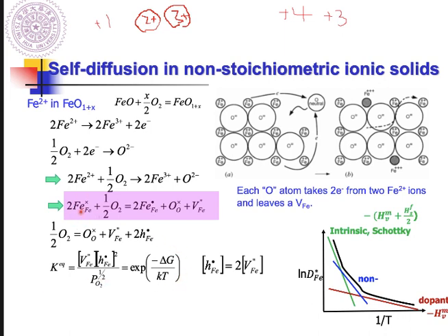So why is this one and this also one? Because most oxygen still occupies the oxygen site, and the iron occupies the iron site, so the fraction is near to one. So you can just put the fraction of OO and fraction of Fe here. So you can rewrite it like this. And based on this equation, the purpose here is you want to know what's the VFe, the vacancy at the iron site. This is what we want to know.